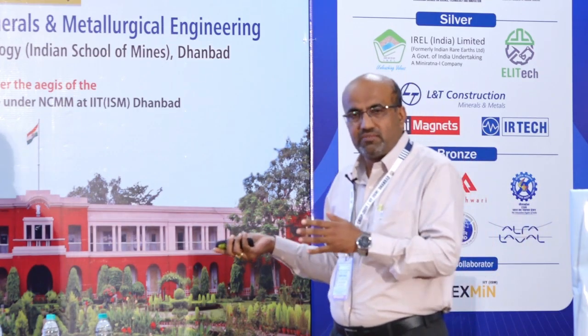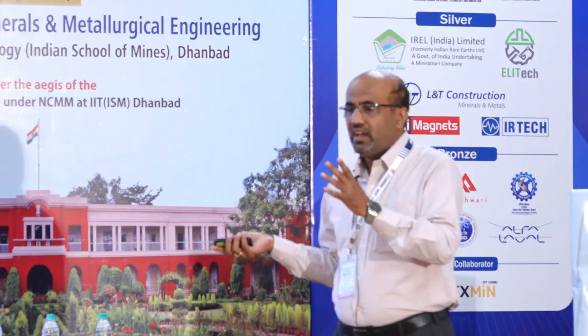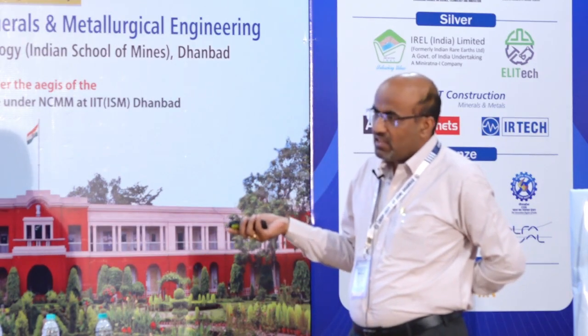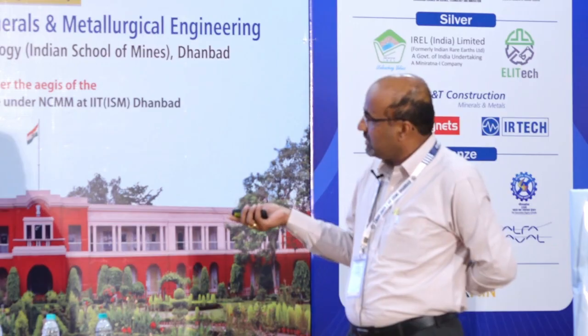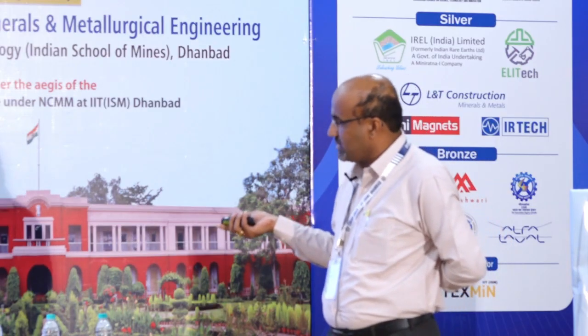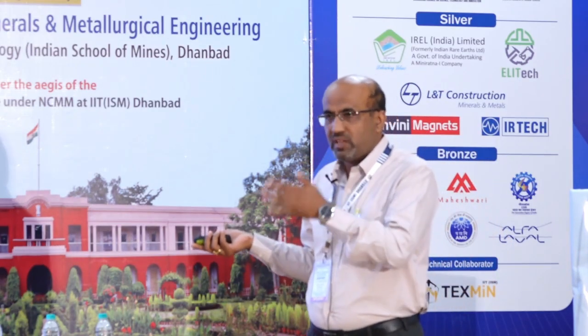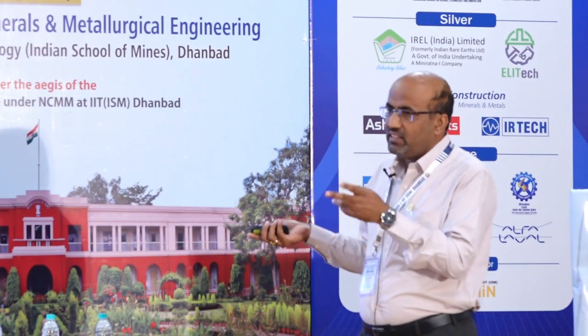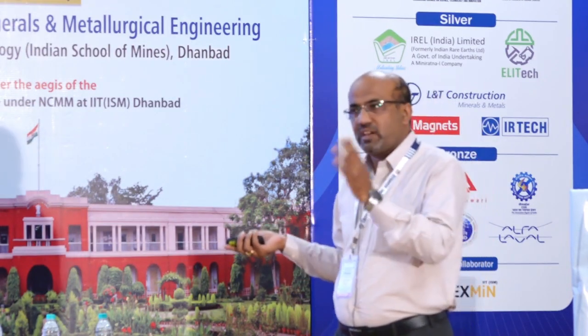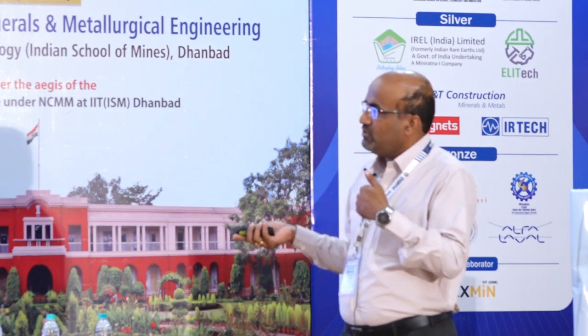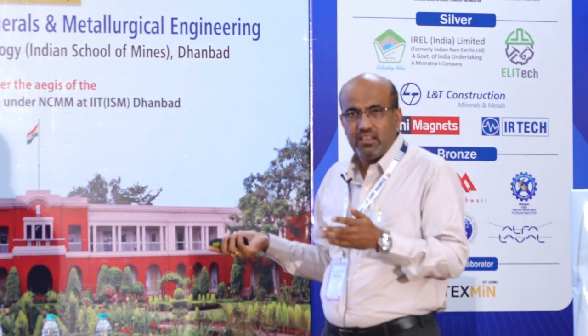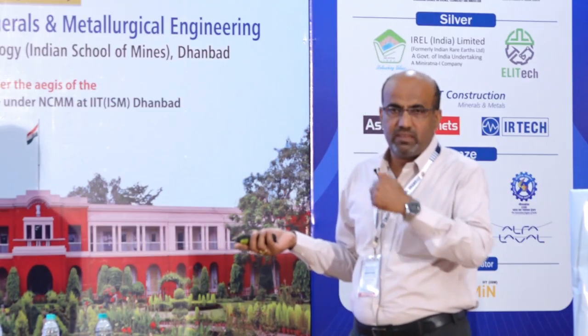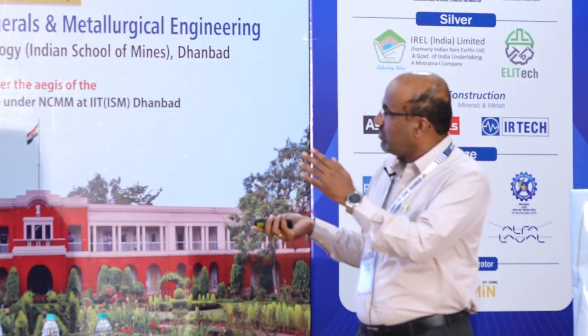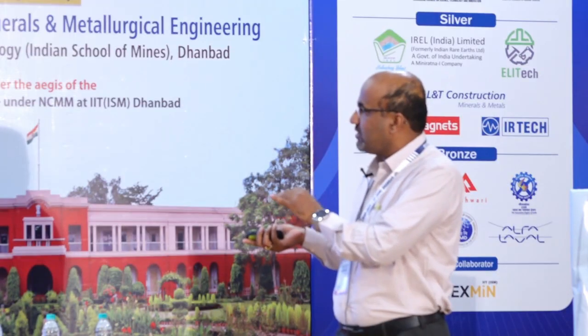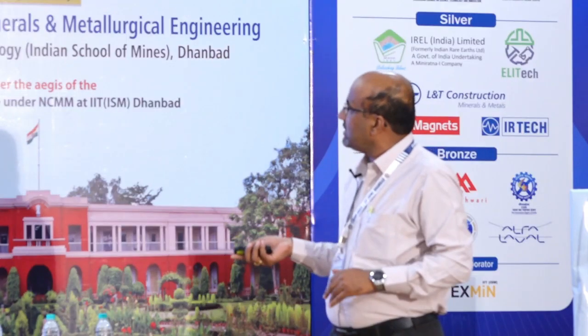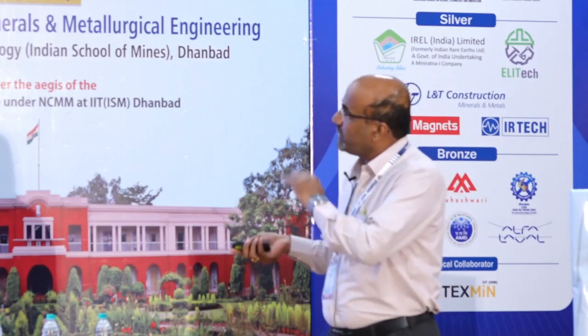When we do DFT and design the ligand, parallelly we do some FTIR, UV and NMR, and other experimental work. When there is a close match between experimentally derived FTIR, let us say, and theoretically derived FTIR, we know that okay, we are hitting the target. After getting the close match, we start with the synthesis. So this is a typical thing.